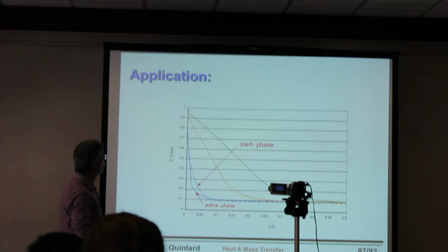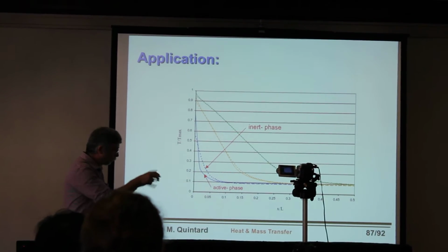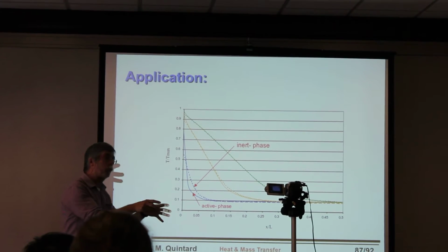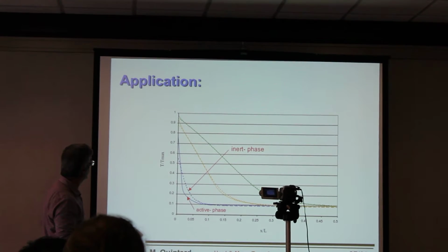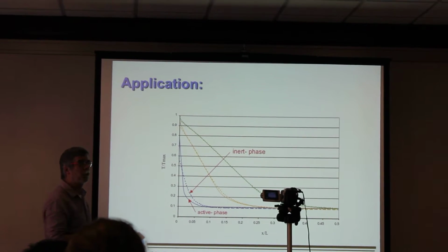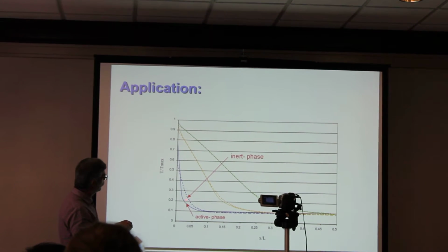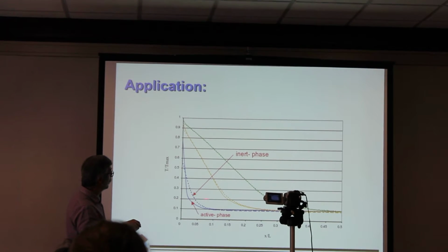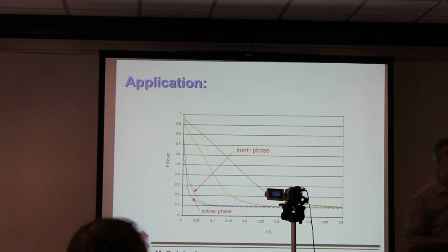And so what's here? This is the temperature. So we have some active phase that will have some sort of pyrolysis mechanisms, and we have the carbon fibers that do not have any chemical reactions, and you see that. I'm not authorized to give numbers, but remember that we have a 1-2 minute time duration. So at the beginning, there is a strong difference, so it's really non-equilibrium. And then after a while, let's say at half time of the entire process, we revert to a local equilibrium situation. So, well, not a big deal.